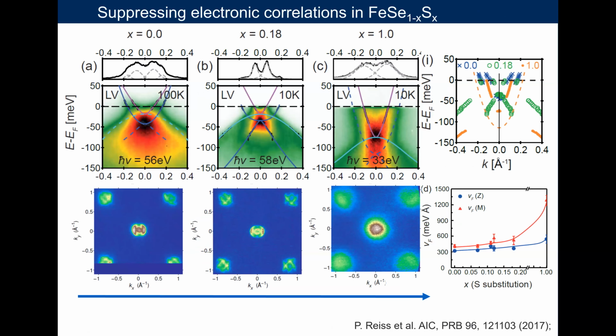This correlation can also be tested with ARPES. This is the iron sulfur end here, which has much steeper dispersion compared with iron selenium. And one can estimate the Fermi velocity and see that it increases significantly as we go towards the sulfur end.